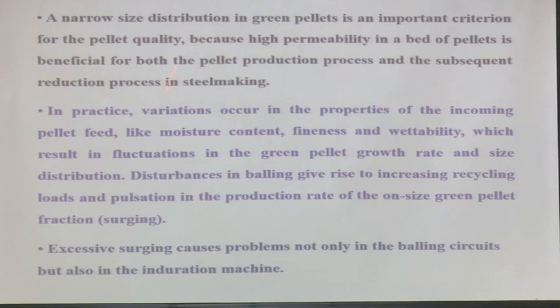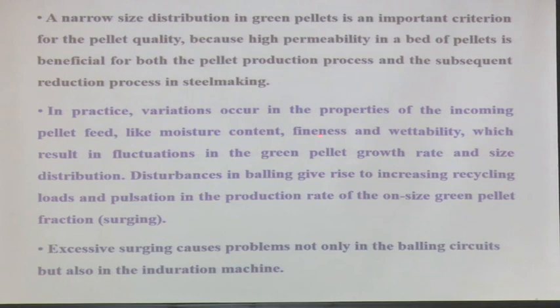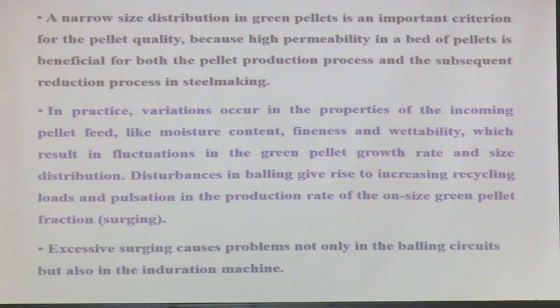A narrow size distribution in green pellets is an important criterion for pellet quality, because with a close size range of particles you can have more permeability in the bed and achieve a spherical shape. In practice, variations occur in the properties of the incoming pellet feed — moisture content, fineness and wettability. Wettability is a surface-related phenomenon controlled by contact angles between the particle and water, which results in fluctuations in the green pellet growth rate and size distribution. The kinetics of pellet formation — the layering mechanism and how each layer is formed — controls the green pellet strength and subsequent stages.